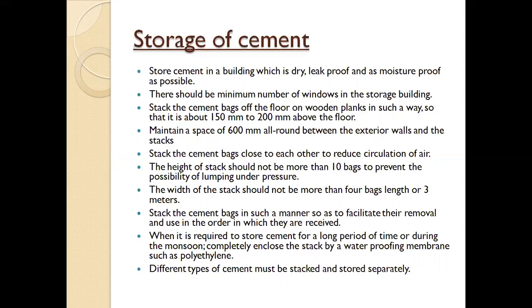More than 10 bags should not be stored in a single stack because, due to the pressure, there may be a possibility of formation of lumps. The width of the stack should not be more than 4 bags length or 3 meters. So the stack width should be a maximum of 3 meters or 4 bags.